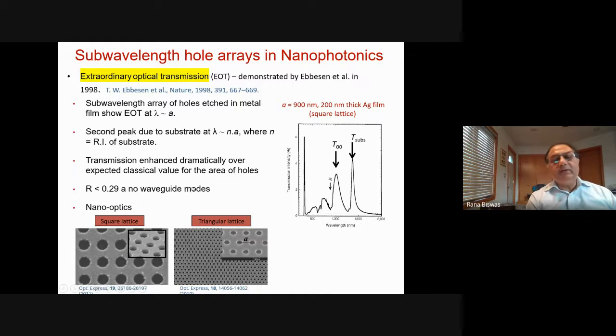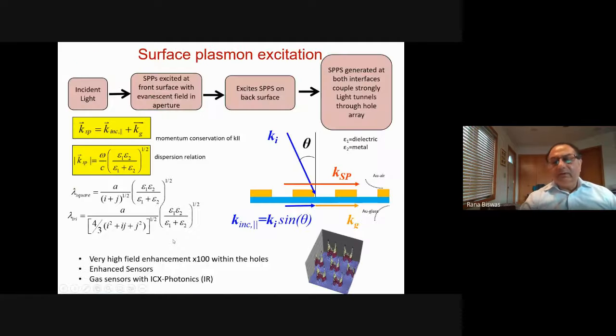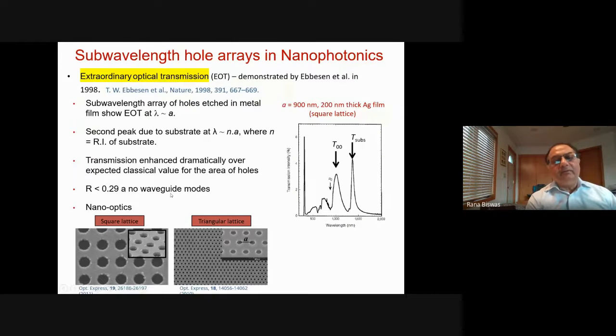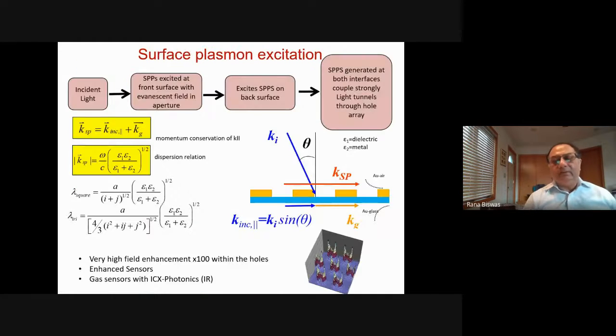For both of these, the transmission is enhanced dramatically over the expected classical value for this area of holes. And the holes are quite small, less than 0.29 times the pitch, so no waveguide modes can propagate through the structure. So this has been a very fertile platform for nano-optics that's been used in many different laboratories.